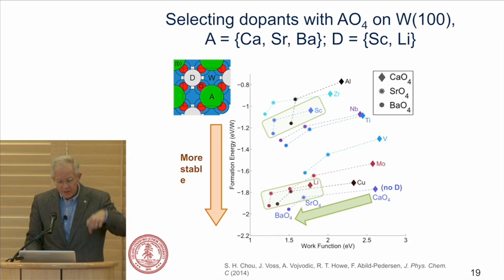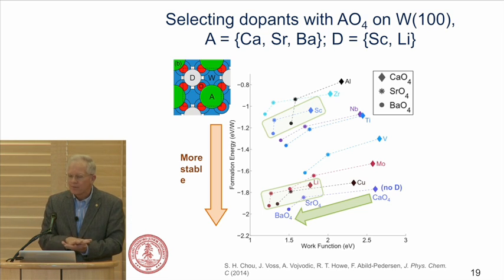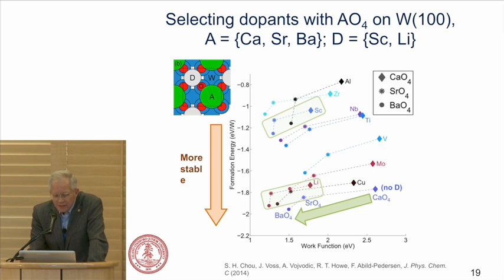We want very large negative formation energies for stability. There are things like dispenser cathodes that spew out some of these materials. We want a rock-solid, stable material. Ideally, for those that are in the electron emission business, we would not want cesium in this. That's a difficult material to deal with, and can we do it with simply our mixed oxides? So we're driving in a direction of low work function and stable formation energy.